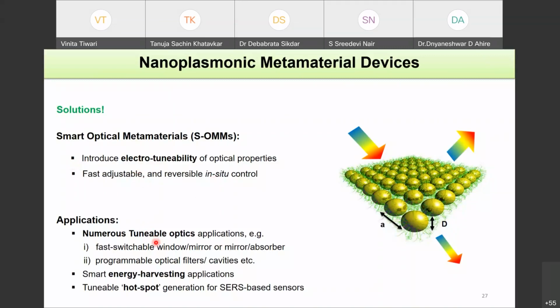So they have numerous applications in tunable optics where you can quickly switch from a window to a mirror state, or you can switch from a mirror to an absorber state. Now, why am I calling it mirror? Because when these nanoparticles are very close packed, they effectively behave like a thin metallic layer. Now, if you take gold metal, that new metallic layer they are effectively forming will have a very different refractive index or permittivity than original gold, but that layer will still have very good reflectivity. So a dense layer of gold nanoparticles can be thought of as a mirror, and a sparse layer can be thought of as a window where light can simply pass through.